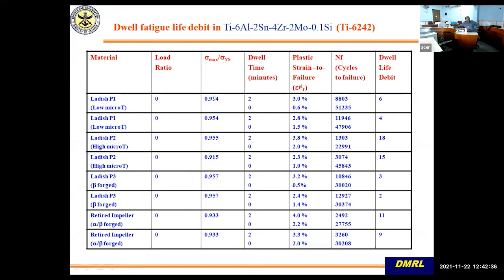Now most of them were tested at around 95 to 91% of yield strength, and a 2-minute dwell time was applied. Here you can see the continuous cycle and the dwell cycles, and the dwell debit is shown here. You can see that the material which has got a higher microtexture shows higher dwell debit as compared to material which has got lower microtexture. And beta forged material, because it has got higher grain size, shows lower debit, but still it has not got very good other properties also. And the retired impeller again shows very high debit, because it was processed much earlier than microtexture was understood in titanium alloys, and people did not understand microtexture properly at that time.